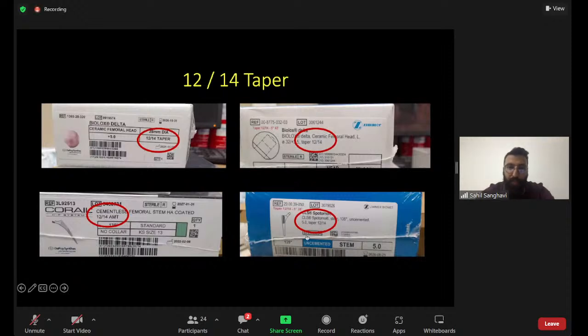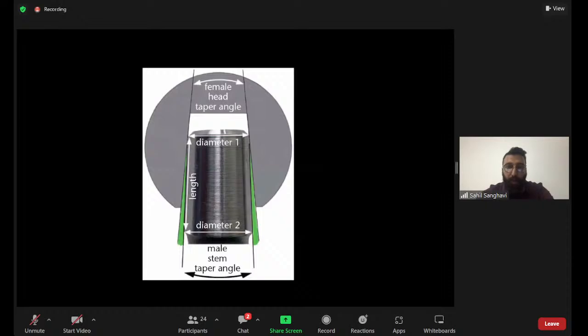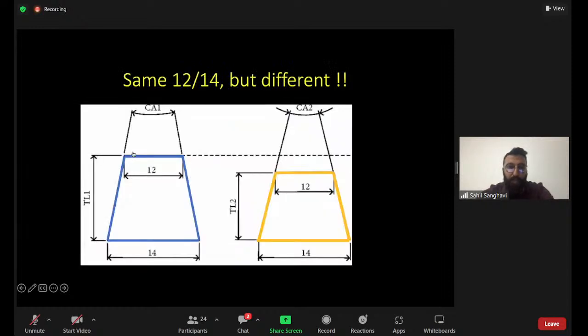So can you use a bearing surface head of one company with the stem of another company? Now this should definitely be avoided because the taper angle is different. When you say 12-14, the diameter on top is 12 millimeters and the diameter at the bottom is 14 millimeters. But here you can see one taper in blue and the other in yellow. And as their height changes, the taper angle changes. So that can again predispose to complications of fracture and trunnionosis.